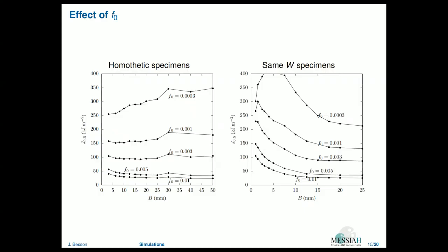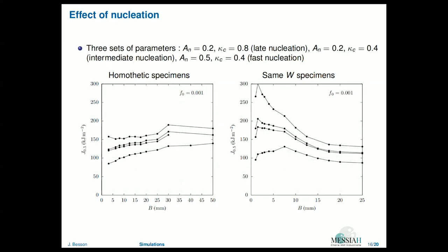If you vary the specimen, you always get that increasing curve, unless you have an initial void volume fraction which is very low, so that you can strain the material a lot, and you can reach a point where you start to have secondary nucleation. In all the other cases, you fail by internal necking without reaching the strain which is needed to trigger nucleation. And that's why the curve is always increasing. Okay? So we can play with the different nucleation rates.